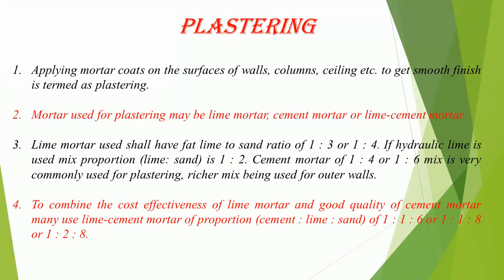To combine the cost effectiveness of lime mortar and good quality of cement mortar, many use lime cement mortar of proportion — cement:lime:sand — of 1:1:6, or 1:1:8, or 1:2:8.